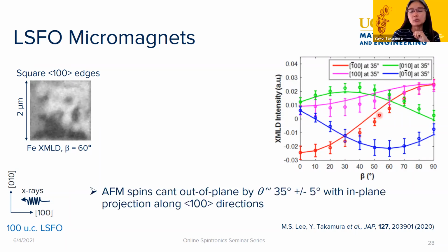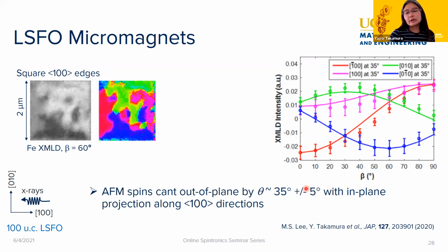And then we can figure out that now the canting angle out of plane is around 35 degrees. So very similar to the thin film before we had patterned it. Then we can also go back to our original image and map out where those different types of domains are, right? And so we have, again, color coded them, so red versus pink, green and blue.